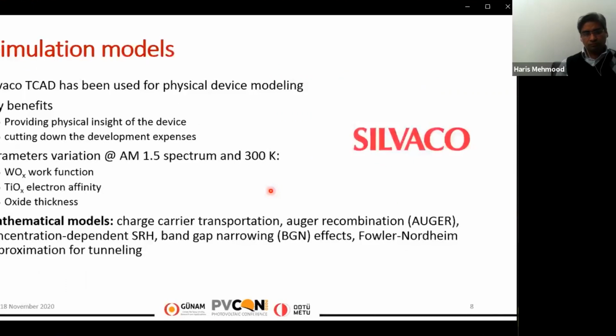For the simulation and mathematical model, the Silvaco ATLAS simulator was used, and several parameters were varied at the AM 1.5 spectrum at a temperature of 300 Kelvin. We have analyzed various parameters by changing the work function of tungsten oxide, as well as the influence of the electron affinity of titanium dioxide on the photovoltaic performance. And in the end, we have checked the effectiveness of the silicon dioxide layer as a passivation layer for our proposed device. The novelty of this structure is that such a solar cell structure has never been simulated before. Particularly, the DASH device employing the passivating silicon dioxide has never been simulated in the literature before, nor has it been fabricated in the literature.